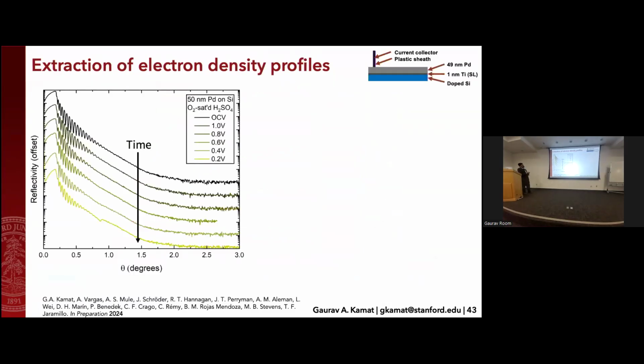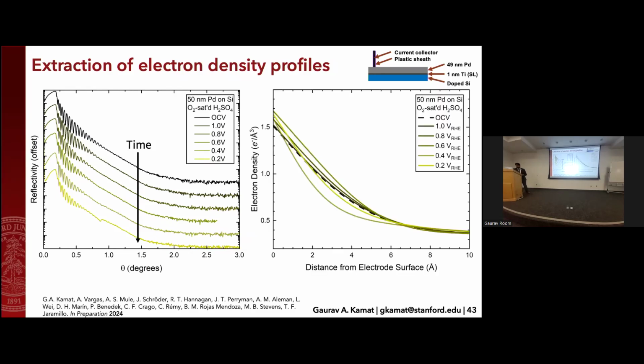And then the last thing you can do with X-ray reflectivity is actually extract electron density profiles, because these X-rays are actually reflecting off layers of electron density, because your sample is very layered, and so is your double layer that's just above your surface. So you can use the reflectivity signal to back out how that electron density looks near your surface. So if we take a data set like this, which was for sulfuric acid, it looks something like this. Compared to open circuit potential, all of these other potentials have very slight differences to electron density. And one interesting thing I'll note is that 0.4 volts here seems to be the one that's tightest or closest to the electrode, because this is distance away from the electrode surface.